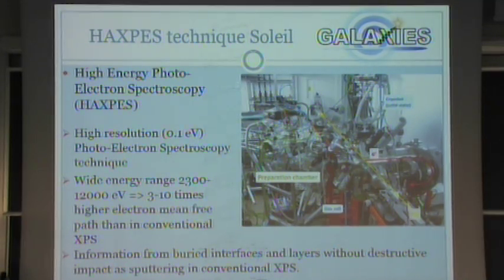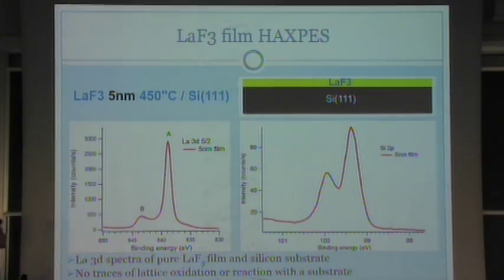was used. Using this technique, you are actually able to register a buried interface. It allows creating high-energy electrons, so you can register, for example, the signal from silicon, which is under 5 nanometers of lanthanum fluoride. Here you can see the silicon interface signal, and this signifies that the interface is clean, with no oxygen or reaction with lanthanum fluoride. And on the left side is a lanthanum fluoride peak, which points to good quality of the sample and no oxygen again. So we've prepared good samples, we've made no errors, which was a good result. But still it doesn't give us an answer where the oxygen comes from.